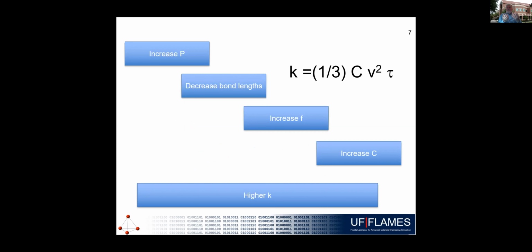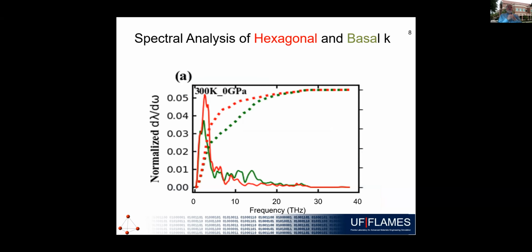Now, those simulation results look very much in the same form as experimental results. And so in that sense, those simulations aren't providing any more information. But we can delve much more deeply into this. We can look at this in various ways. So for example, this is a spectral analysis. This is showing what fraction of the heat transport is carried by phonons of specific frequency ranges. And this is showing it for the hexagonal and the basal phonons.